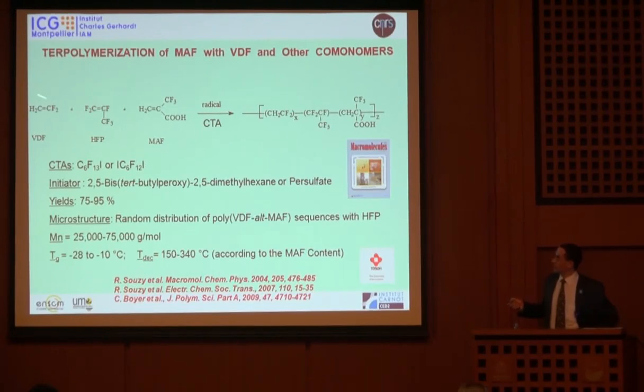And interestingly, it's a very good comonomer for VDF, so you can make a PVDF with carboxylic acid, which is very interesting because carboxylic acid can be modified and even you can attach some nanofillers inside. So the idea was to make telomerization under conventional polymerization or in the presence of the chain transfer agent in order to make some controlled radical polymerization. I will speak about that in another seminar. And the different chain transfer agents can be either iodo compound or diiodo compound. Initiator can be different peroxides or persulfate. We can work in water or in solvent.